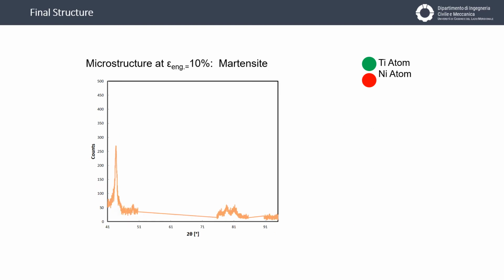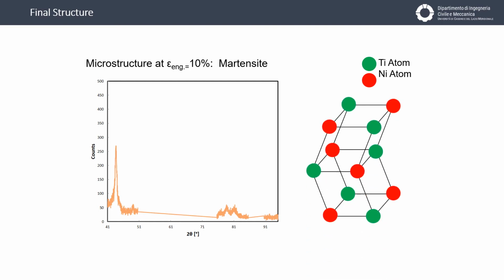Considering the spectrum obtained at high values of deformation of the specimen, with an engineering strain of 10%, we can see that the first peaks disappear, and we have the presence of another peak in this position, and another one here and here. Analyzing the structure, we discover that the new structure is a monoclinic structure like this, and here we propose the position of nickel and titanium atoms on the vertices of the structure.